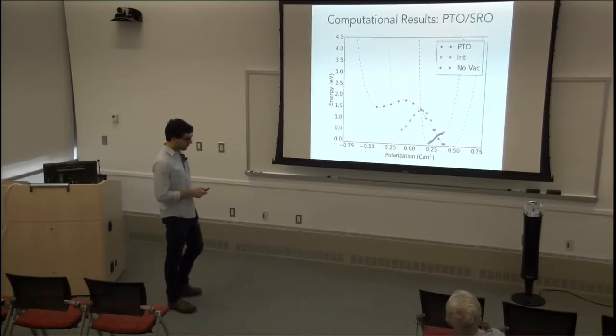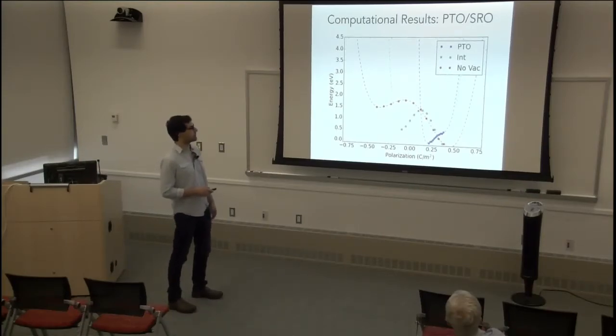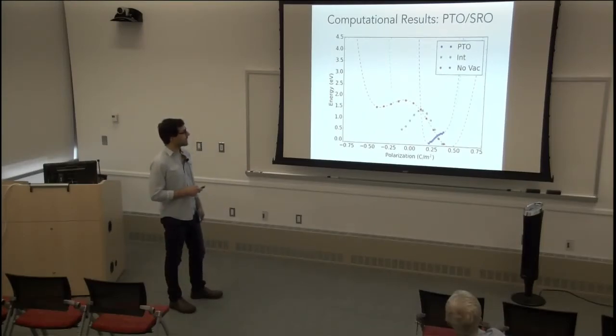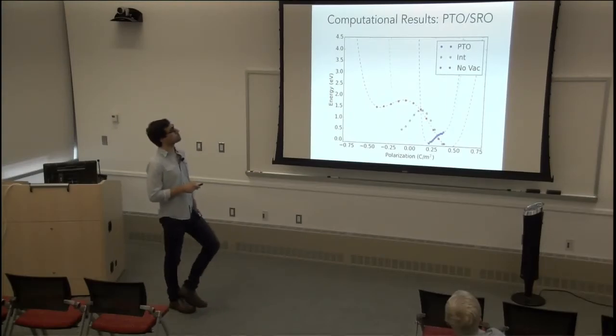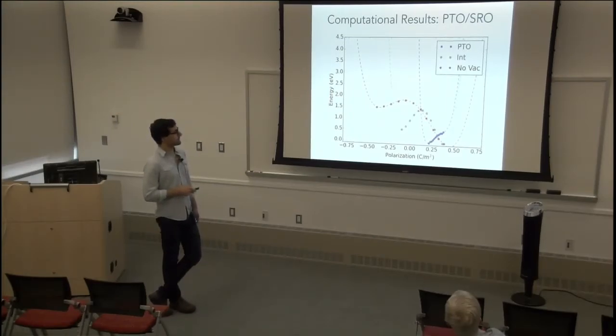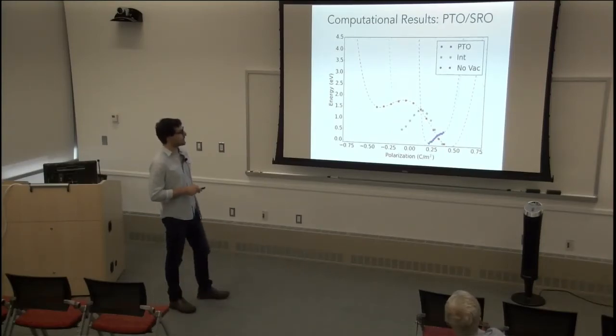Another thing, if you remember, we saw a reversal in the trend with the PTO volume fraction. What we believe is happening is that when you have a low amount of lead titanate unit cells, this state is preferred. If you have a high amount of lead titanate unit cells, this state becomes preferred. Now clearly here, this is not the case, it's still this right state that's preferred, but we believe if we did a larger simulation, this state would go down even further, and then this would become the more stable state compared to this state.